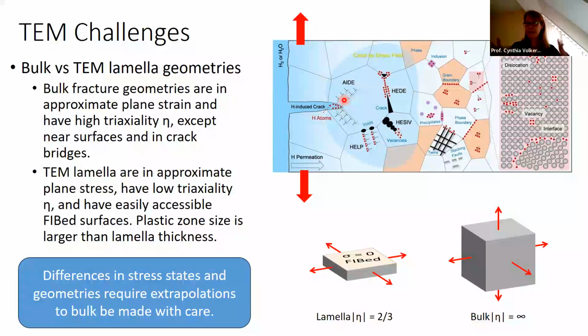And if we think about a bulk specimen, then out of the plane of the view graph, the material extends infinitely or quite a long ways. And so the stress state here is what's known as plane strain, and the so-called triaxiality is high, which means that plasticity is low. If this is a thin film like a TEM lamella, then plasticity becomes much, much higher. We're in a situation of plane stress. And the nature of the stresses, this triaxiality, whether all the stresses in all three directions are equal, is what triaxiality is a measure of, is very important because it controls the amount of plasticity that can go on. And this is completely different in a TEM lamella than in a bulk specimen. And this is a difference that we cannot ignore.